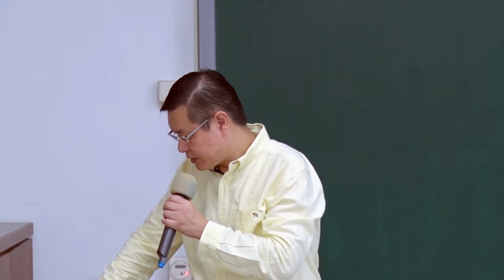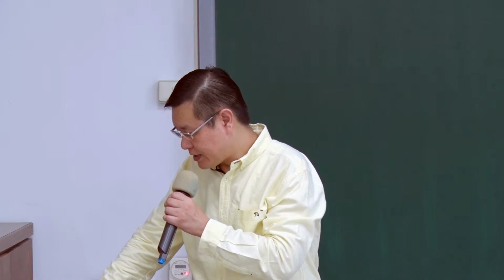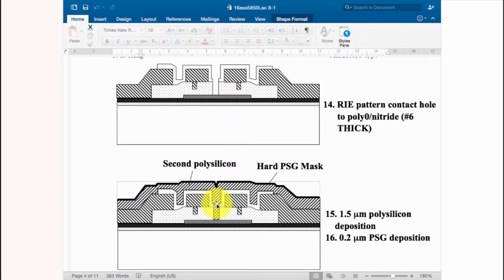So in the center part, as you can see, we have already applied the thick command here. So we have the hole all the way down to the bottom. So in the center part, the second polysilicon can be used to connect to the bottom poly0 substrate surface. But for the other area, we only cut through the second sacrificial layer. So we can make the connection between the second poly and the first poly. So in the center, we can contact the second poly to the poly0. On the border, you can contact the poly2 to poly1. Okay, poly2 to poly1. So it depends on whether you apply the thin command or thick command at the side or at the center.